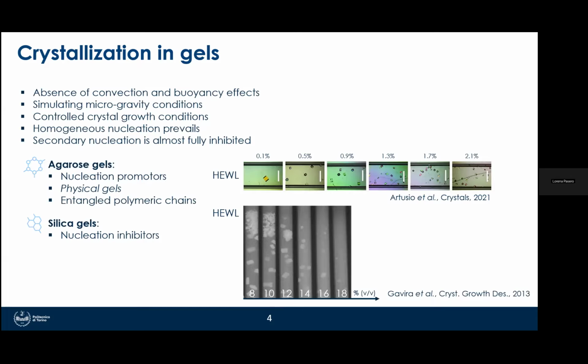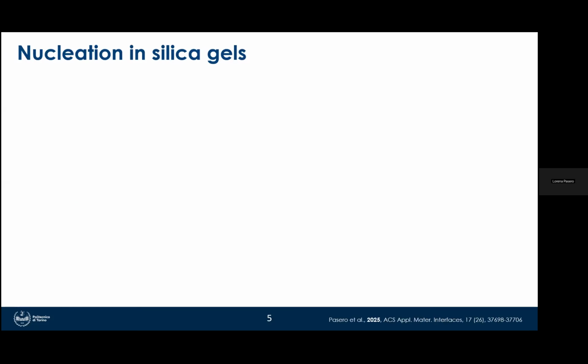These gels can act as inhibitors on nucleation since when the concentration of the gel was increased, there was a decreased nucleation of lysozyme. And they also differ from agarose gels since they are chemical ones, where the gel is constituted of cross-linked polymeric chains. So here comes the main question, which is why does silica inhibit nucleation and how can we control it? And to understand this phenomenon, we should first look at how silica gel forms.